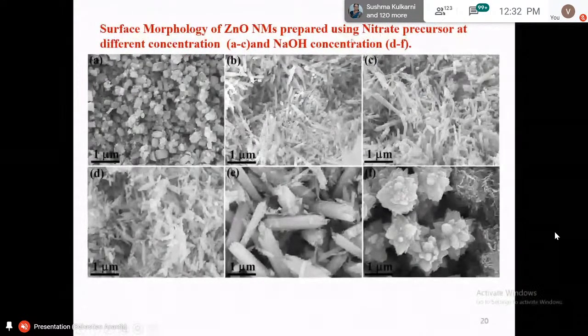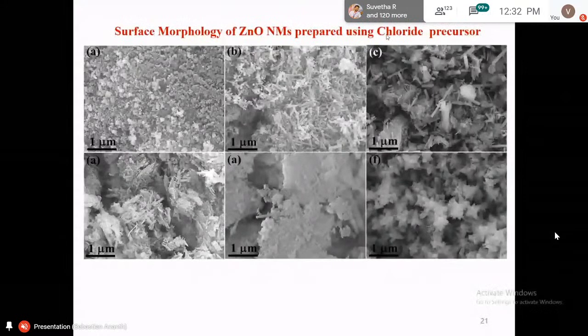And also we use zinc nitrate as the starting precursor. Suppose instead of zinc nitrate, we use zinc chloride. What happens? These are the surface structures we get. So here another finding is also coming. The raw material, the nature of the zinc precursor, is also very important for getting different nanostructures. When you use chloride, we get two kinds of things. One is a rod-like zinc oxide, and then a kind of flower. Here also we get flower, but here are different structures.